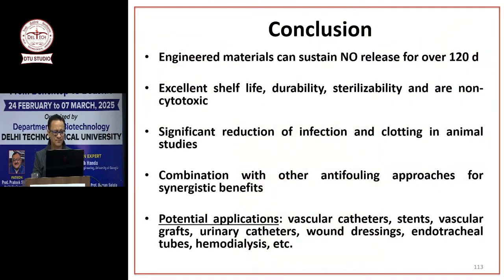So to conclude, we did a lot of things today, but the main thing is we can release nitric oxide for long periods of time, right? That was one of the challenges when I started working in the field. We can swell or impregnate SNAP into the walls of the materials, so we don't have to extrude. That was another challenge. We can sterilize it. It is shelf stable, which was another challenge. NO releasing materials do not prevent protein absorption. So we can combine it with super hydrophobic material, super hydrophilic material, slippery material. So we can take care of that, NO plus anti-fouling.